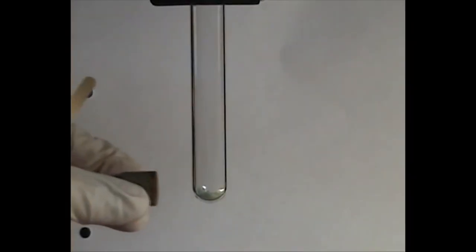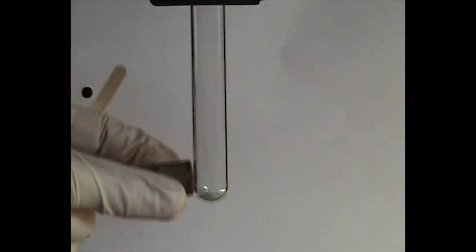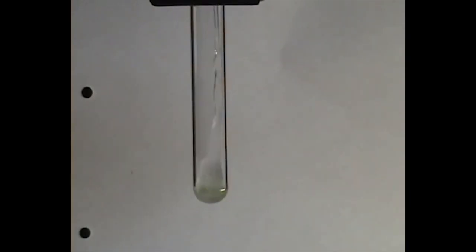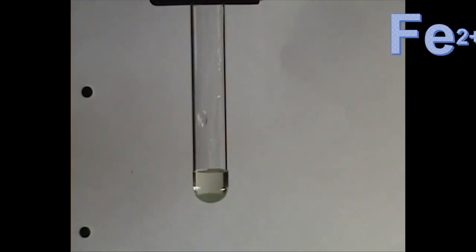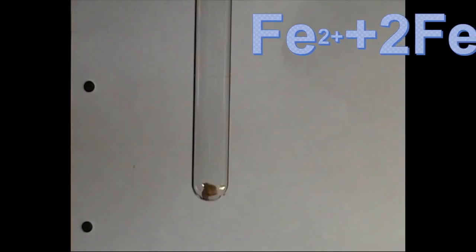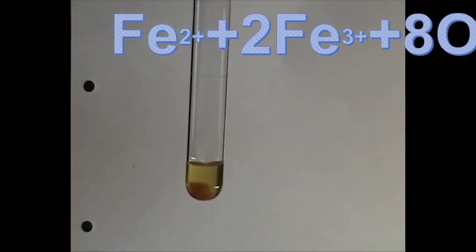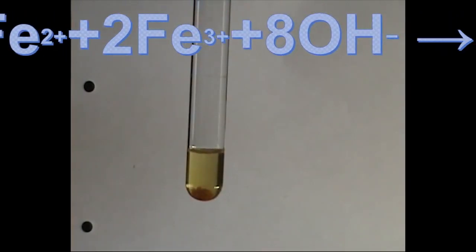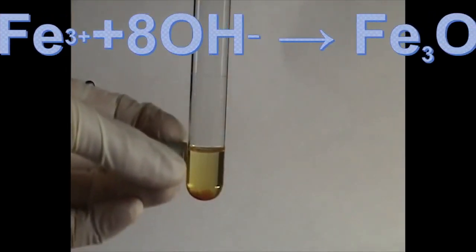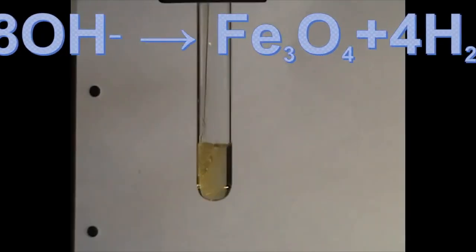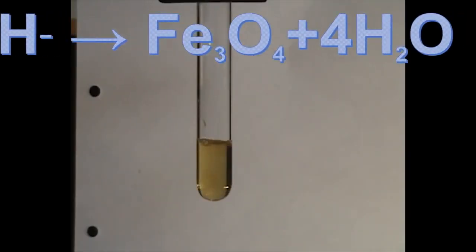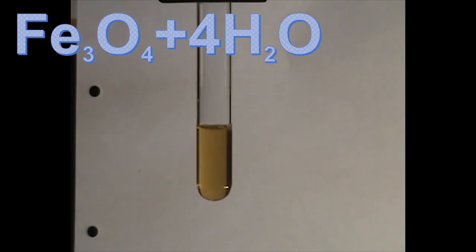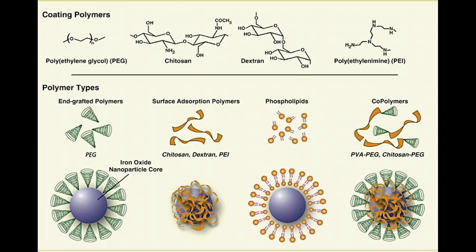To produce the structures that hold and transport the luciferase enzyme used for bioluminescence, iron oxide magnetic nanoparticles, or MNPs, must be synthesized first. To create the MNPs, a solution of ferric and ferrous ions is combined with a base, usually hydroxide. Magnetite then precipitates from the solution. Polymers or organic molecules, such as citric acid, are also added to prevent excess products from gathering on the surface of the MNPs.